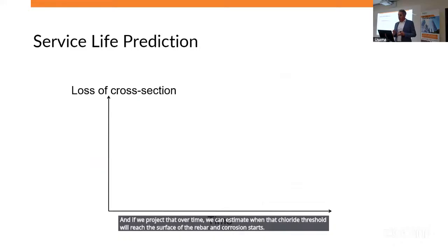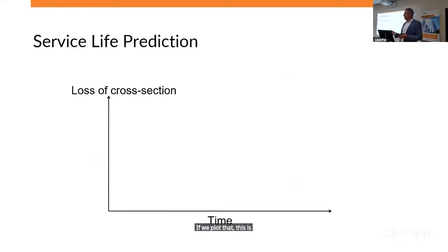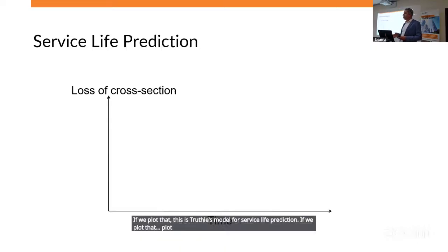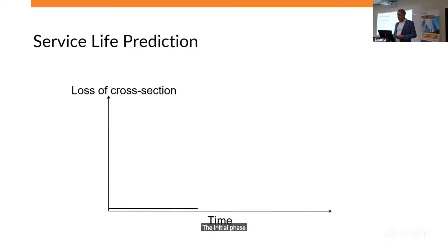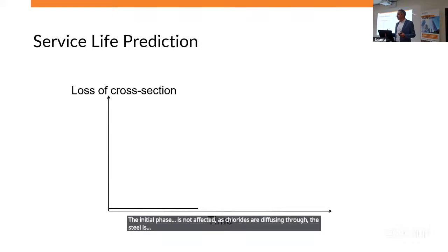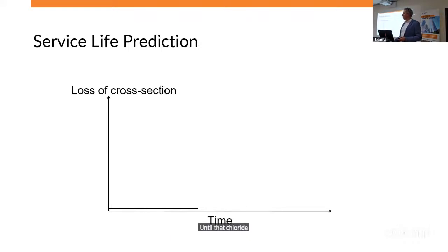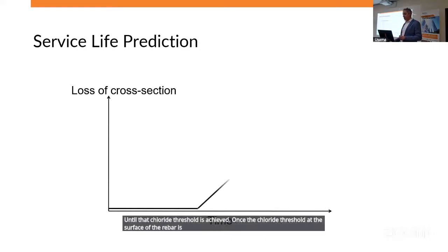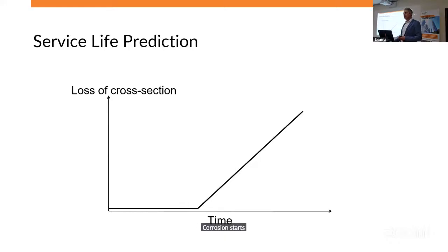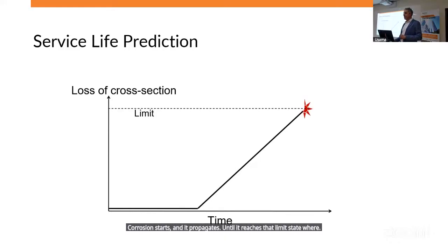If we plot that, this is Tuutti's model for service life prediction. If we plot the loss of cross-section of the rebar over time, the initial phase is not affected. As chlorides are diffusing through, the steel is not damaged. There's no loss of cross-section until that chloride threshold is achieved. Once the chloride threshold at the surface of the rebar is reached, corrosion starts and it propagates until it reaches that limit state where cracking occurs.